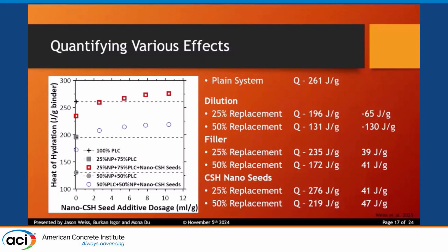Well, part of that heat is going to simply come from the filler effect. Remember, by separating those particles out further, I can actually quantify the filler effect, and that's this point to this point. There are no nanoparticles in the system. I've added about 40 joules per gram back into the system just due to the filler effect, just due to using the clinker more efficiently. I still have more to make up, so I can add in the nano seeds, using a very low dosage, and I can make another 40 to 45 joules per gram of that material up. What you'll notice is there's a general increase as you increase the dosage, but there's sort of a law of diminishing returns.